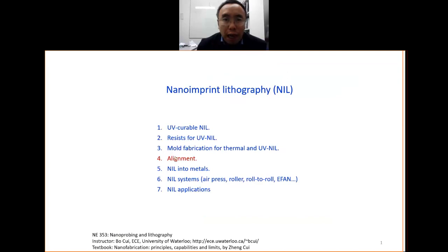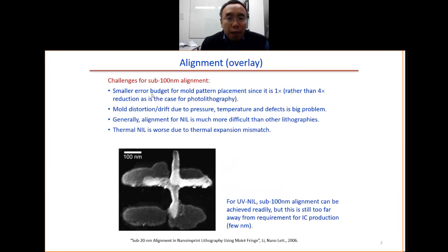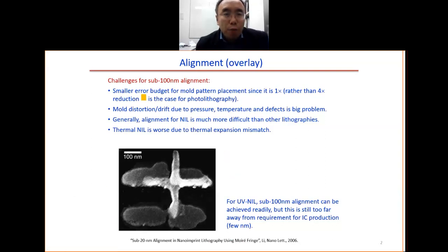So now let's look at alignment for the imprint lithography. There is a big challenge for the alignment for imprint lithography because we have a smaller error budget. For the case of imprint, we have this 1 times error. That means if the misalignment is 10 nanometer, then you get an error of 10 nanometer. But for the optical lithography, you have 4 times reduction. If we have misalignment of 10 nanometer, it will become 2.5 nanometer.